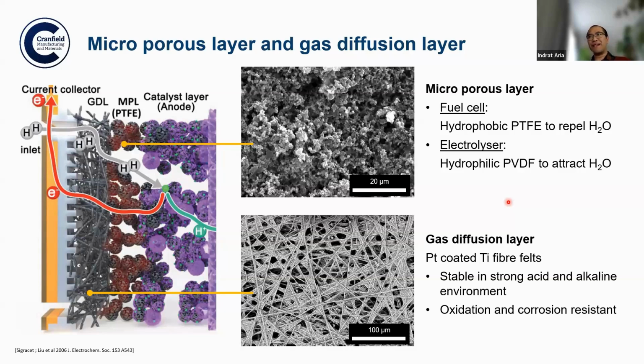On the other hand, for electrolyzer, the fluorinated polymer has to be hydrophilic because you want to attract water. Water will be split by the catalyst, right? So you want it to be hydrophilic. The gas diffusion layer basically interfaces the backing plate and the current collector with the microporous layer.